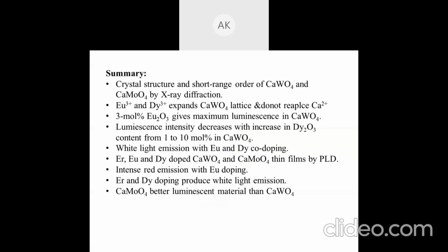And we unambiguously answer the question that europium, dysprosium, and erbium ions do not replace the calcium sites in the tetragonal crystal structure of bulk materials. And rare earth ions expand the calcium tungstate lattice. 3 mole% of europium oxide gives maximum luminescence in calcium tungstate.